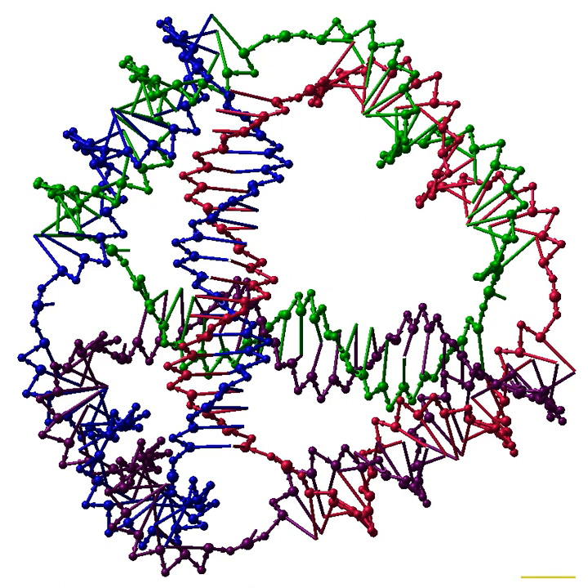Many schemes use a covalent attachment scheme, using oligonucleotides with amide or thiol functional groups as a chemical handle to bind the heteroelements. This covalent binding scheme has been used to arrange gold nanoparticles on a DX-based array and to arrange streptavidin protein molecules into specific patterns on a DX array. Carbon nanotubes have been hosted on DNA arrays in a pattern allowing the assembly to act as a molecular electronic device, a carbon nanotube field effect transistor. Additionally, there are nucleic acid metallization methods, in which the nucleic acid is replaced by a metal which assumes the general shape of the original nucleic acid structure, and schemes for using nucleic acid nanostructures as lithography masks, transferring their pattern into a solid surface.